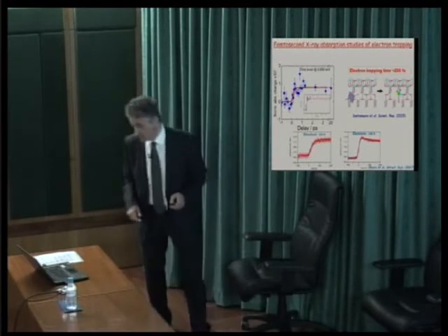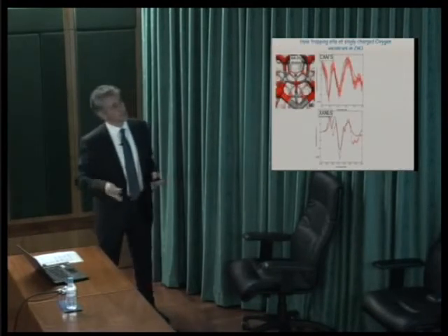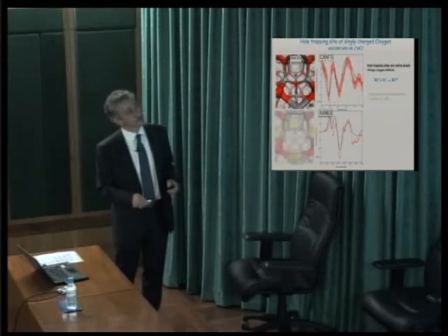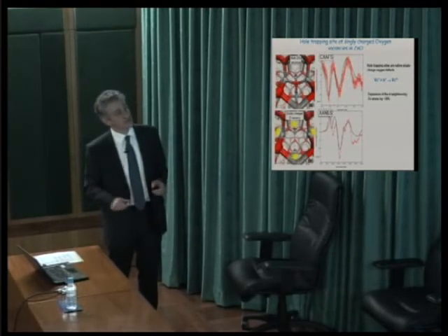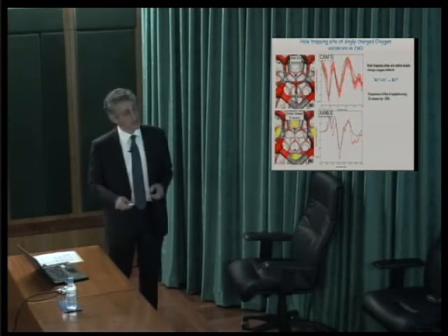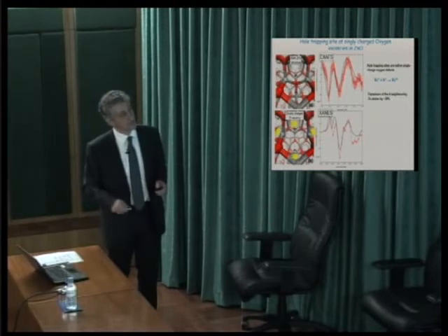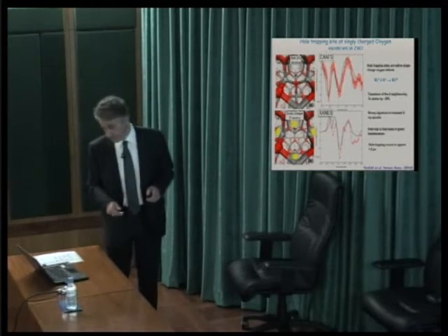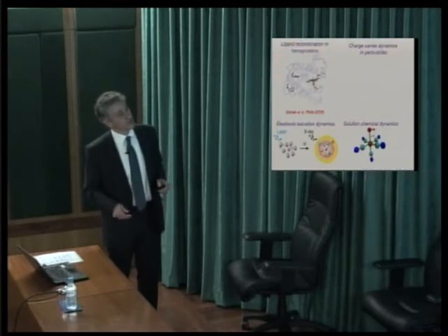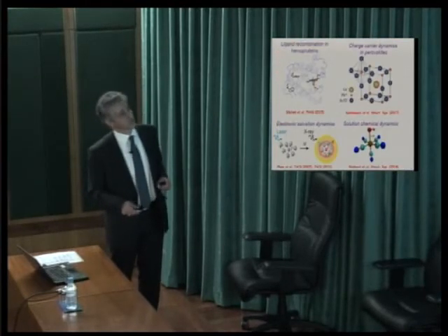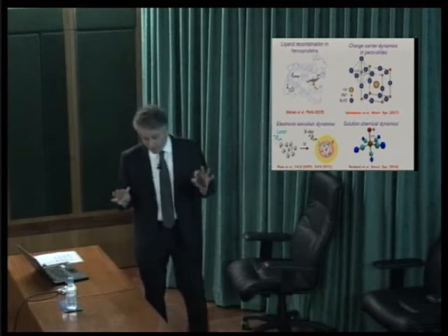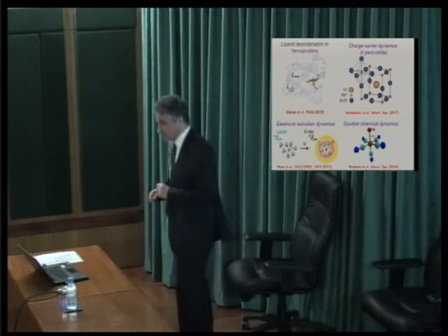of the electronic response. Okay, again, we did recently work on zinc oxide, where we found the trapping of holes, this time at oxygen vacancies, and I don't want to go too much into detail. This just appeared a couple of weeks ago. Okay, I just gave you a flavor about what type of studies we did.